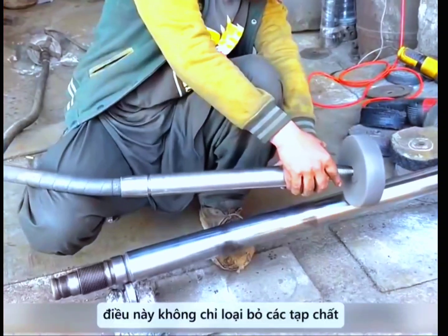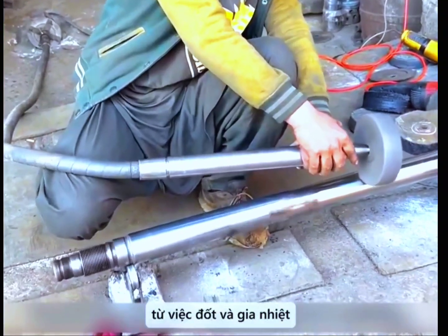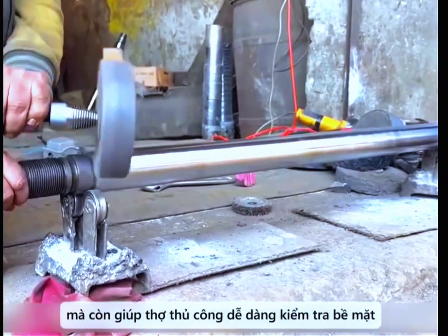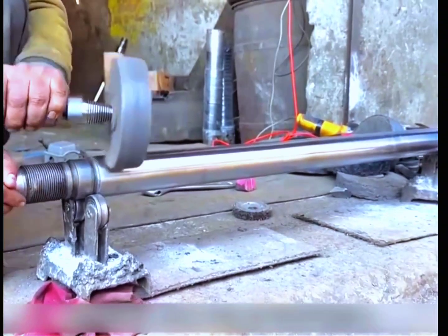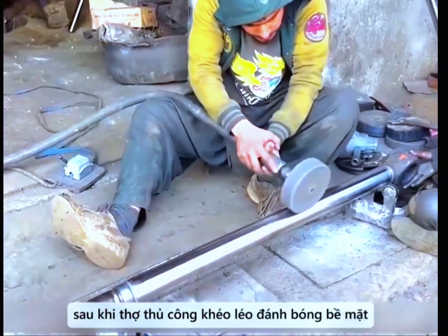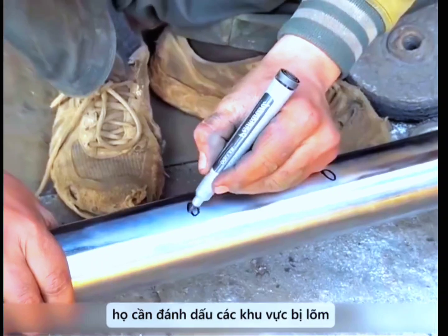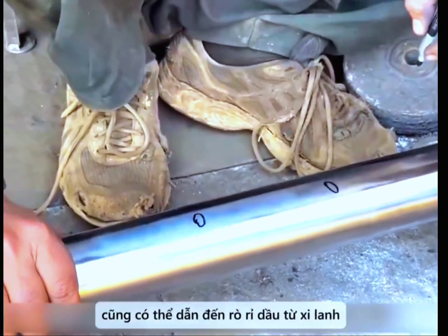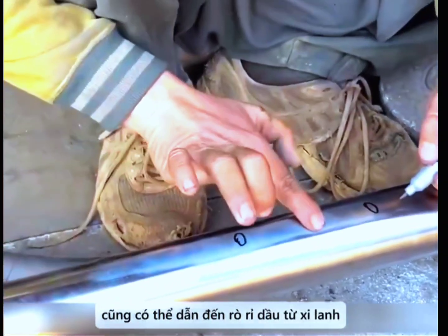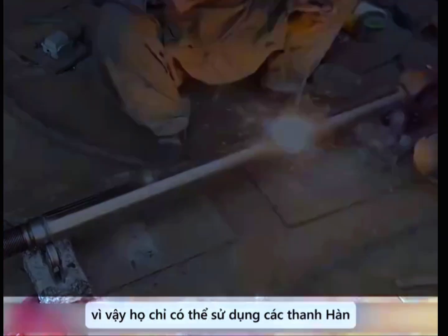After the craftsmen have polished the surface, they need to mark the concave areas because these bumps can also lead to oil leakage from the cylinder. Therefore, they can only use the brazing rods to rebuild the concave areas. The main goal is to fill the concave areas. Because the surface of the brazing rod is very uneven, in order to keep it consistent with the outer diameter of the piston rod, a layer from the brazing rod surface needs to be completely removed.